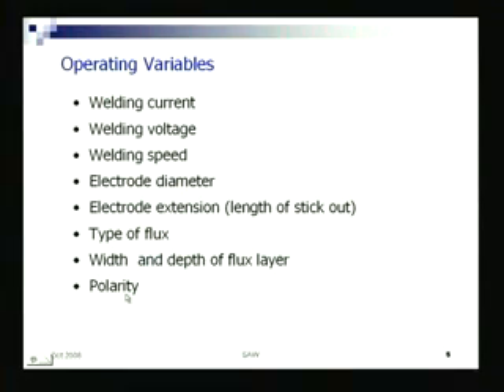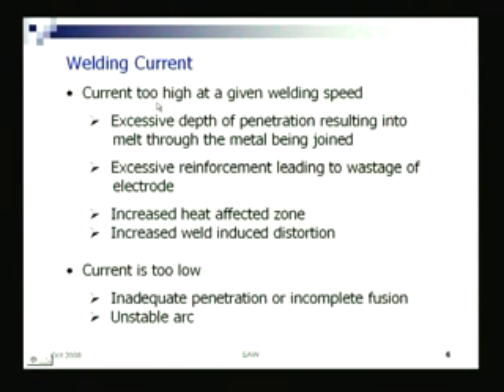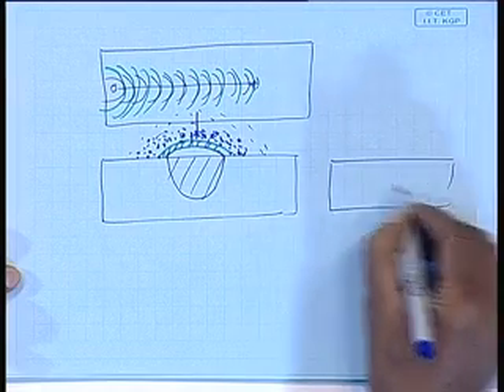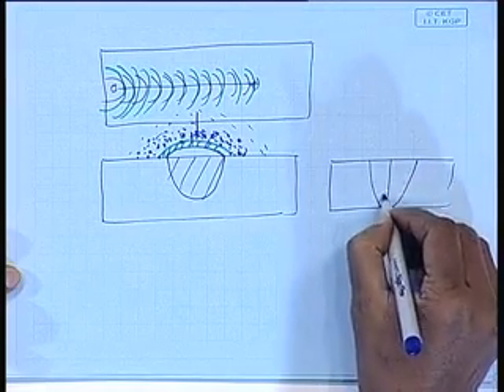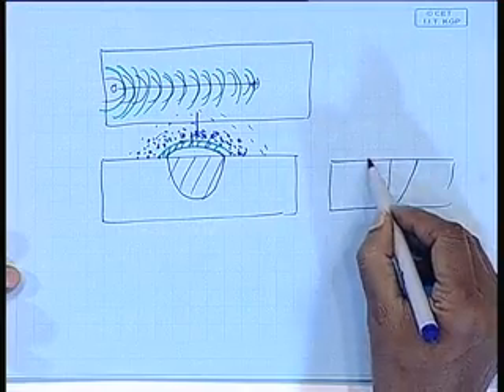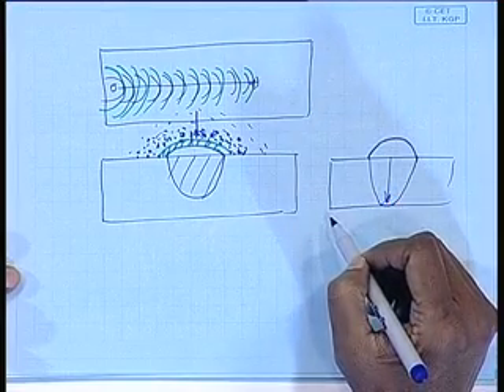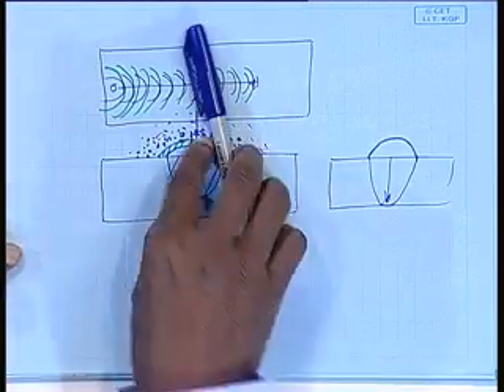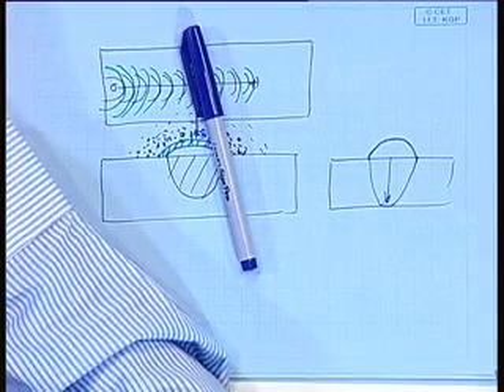And finally, polarity is also important because of the heat generation. If the welding current is too high, there will obviously be excessive depth of penetration and excessive reinforcement, leading to wastage of electrode. High current will produce a much bigger penetration. If the speed is low, then again there will be too much melting. Nothing excessive is desirable, that is the thing.